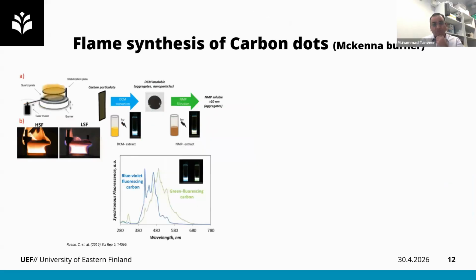The other option for flame synthesis routes can be the McKenna burner. This is really a good system. It has provided quite good insights for the production of carbon dots through flame routes. Here you can see the setup of the McKenna burner. They have used a high-sooting flame and a low-sooting flame, and then collected the particles on a glass plate, and these collected particles are then post-treated with different solvents. They have used dichloromethane to extract the small, very fine nanoparticles, and then they have used NMP for the larger particles.